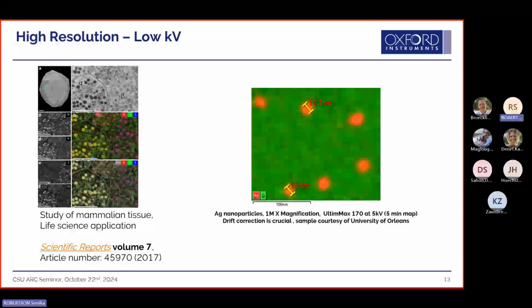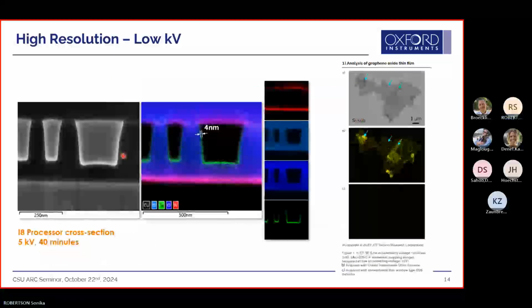But here's another example for tissue. I don't think anyone here deals with it, but in case you ever do, hey, you have the tools to characterize that too. Because with biological samples, again, the requirement is low kV, and that was historically just a challenge because at low kV, we're running into issues of, well, even my 20 kV takes me half a day. So what am I supposed to do? Dropping down to 5 kV, like spend a couple of days just doing that? It just was not practical. But that's not the case anymore.